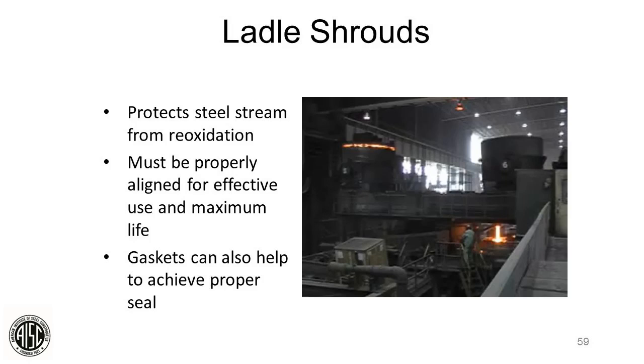So ladle shrouds, on the right-hand side, you see the glowing tube next to the operator there. Its primary job, again, is to keep oxygen from getting to the steel. What you're seeing there is 2 ladles on a turret arm. He's operating on one. There's the shroud. And his job is to make sure, we got to insert that manually, so we hook that up there with a manipulator arm. We open the slide gate, and then we let it run. It pretty much positions itself, but you got to hook it up initially by yourself. Sometimes gaskets get added to achieve a good seal in some shops. Next slide, please.